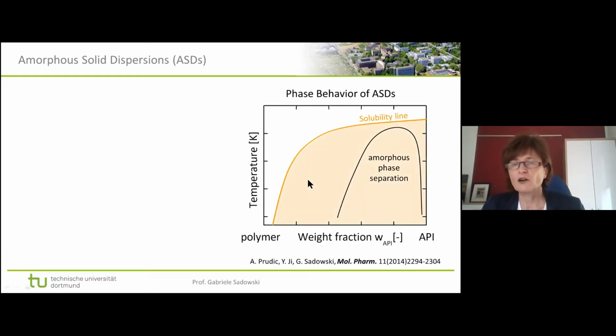So let's look first at the orange line. This is a solubility line, and this means that whenever we have a mixture in the orange area, at a given temperature we would be supersaturated, at concentrations to the right of the solubility line. This means, of course, that being here, we get API crystals. The API will recrystallize and we will end up here, and in the remaining mixture we will have a concentration along the solubility line. So whenever we are in this orange region, we get API crystals, and this is actually what we don't want to have. We want to have an amorphous formulation. So it's very important to know where the solubility line is.